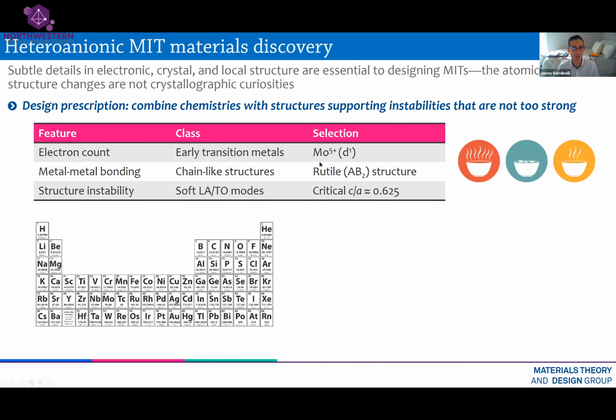And what we will do is choose a compound. So we're going to start with this rutile-like compound. We need to have a particular electron count, and that leads us to select molybdenum 5+, which is d1. I already told you about the chain-like structure in rutile. This will give us that metal-metal bonding between the molybdenum atoms. And then we need to have a structural instability. And this is where the ratio of the lattice parameters is around 0.625.